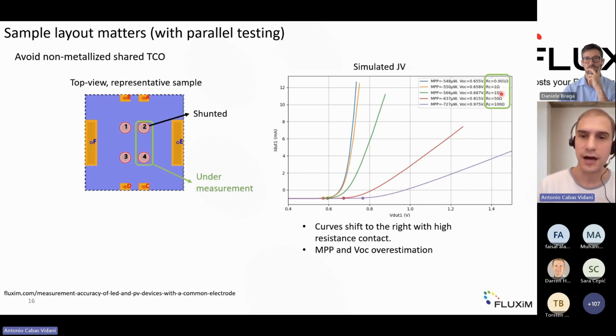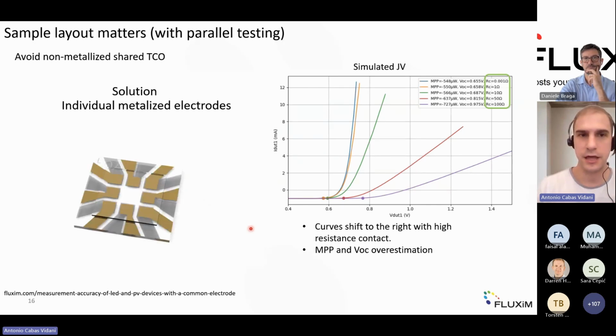Now we can see that the higher the contact resistance, the higher the resistance of the common electrode, so to speak, the more the curve shifts to the right, the higher the overestimation of your MPP and the VOC. So I guess it's quite evident here the importance of avoiding a common electrode and possibly avoiding high contact resistance. And this is why the solution is to have, yes, you can still have multiple pixels on the same substrate, but ideally the contacts should be individual for each pixel, and they should be metallized.